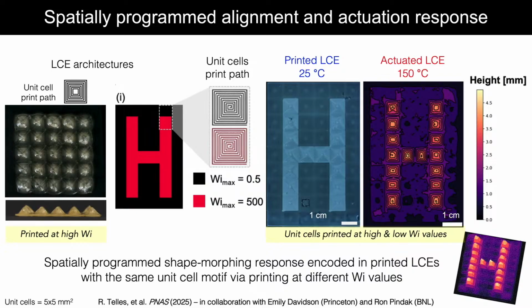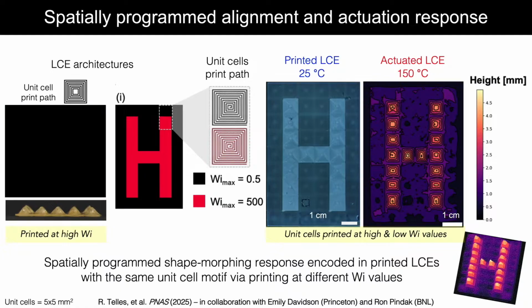So that's kind of interesting, because what it lets us do at high Weissenberg number, of course, in the uniform state, we're printing these little square spiral cells, and once we heat this above the isotropic temperature, all of these little cells uniformly pop up out of plane, right? Because we've encoded alignment along that direction in each of those unit cells. And when they want to contract, they go up laterally, out of plane.